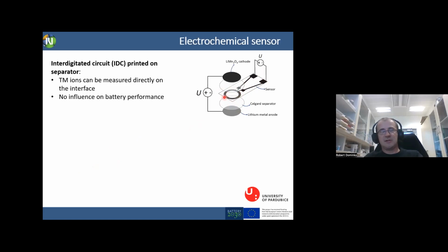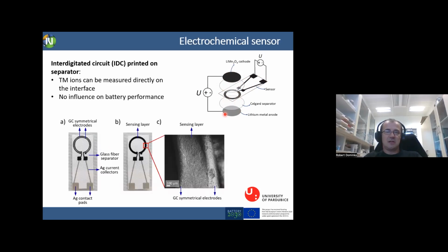We tested different geometries, and at the end we found out that this geometry, which fits more or less the circle of the electrode, provides the best, most reliable and most repeatable results. We also checked that this has no influence on the battery performance. And so now we have these two electrodes, and then we have a connection to the electrodes and contacts.